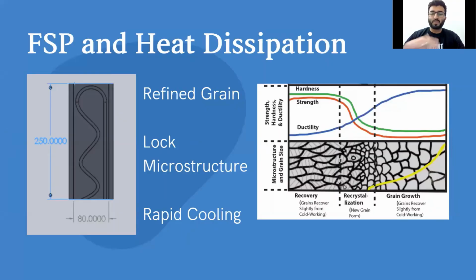As we are doing multiple welds, the heat remains inside the plate and it's not distributed evenly, which promotes grain growth. As you can see in the chart here, grain growth leads to a drop in the mechanical properties, which is undesirable. In order to lock the microstructure that is achieved, we need to cool it quickly, and this fast cooling will lock the microstructure and prevent any grain growth.